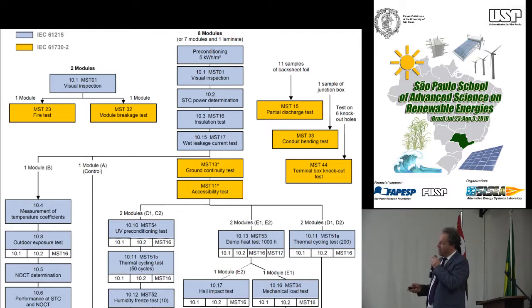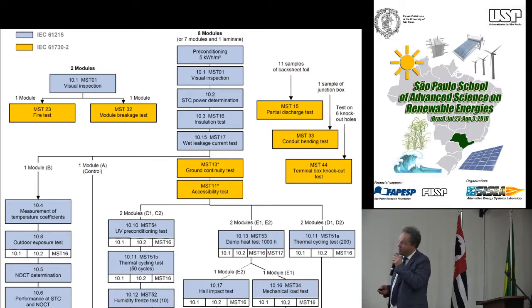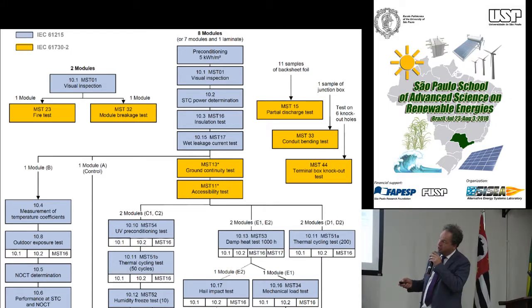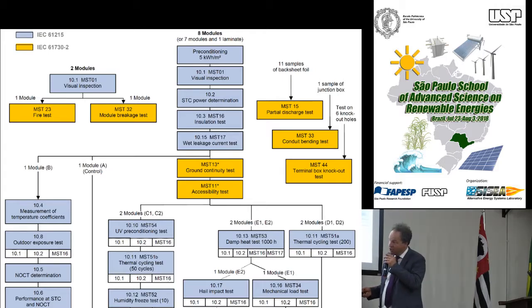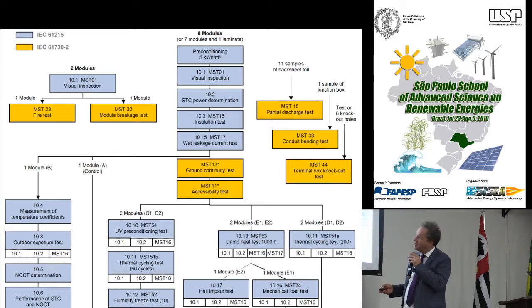Then you have here the hail impact test. Then you see the hail cones, which have a hail impact there. A mechanical load test. You see whether you put some mechanical load on it, whether the module suffers by that. These are some kind of outdoor tests where you are using the data to measure the temperature coefficient. You have an outdoor exposure test of 60 kilowatt hours. NOCT, remember what that means? Nominal operating cell temperature. So you see the more realistic NOCT temperature here and performance here at NOCT.